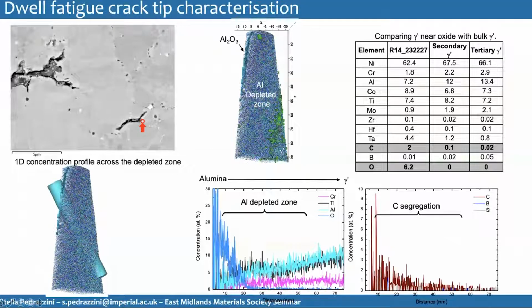The atom probe, like the EDX, could have been quite difficult to interpret because sulfur overlaps with molybdenum. But in the atom probe, there wasn't any sulfur in the other two needles, and there is no sulfur at the alumina gamma prime interface either. There is some carbon segregation and a little bit of silicon impurities, but the sulfur didn't go there either. So atom probe has a lot of advantages.